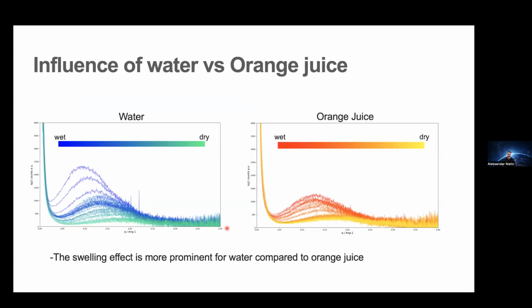Then I think, I don't know how scientific this is, but it's at least a fun example that, of course, you very rarely use a straw to drink water, because that's kind of boring, but maybe use it for orange juice. And what was most surprising, at least to me, maybe the others were expecting this, but to me, you can see that there is a big change in the swelling between orange juice and water. And here you can start to speculate, is it the pH or maybe slower diffusion or whatever that is causing it? But you can see that also these kinds of things you can investigate, where we see a much more prominent swelling for water compared to orange juice, which I think from an application point of view probably is quite good, that it's more resistant to orange juice.